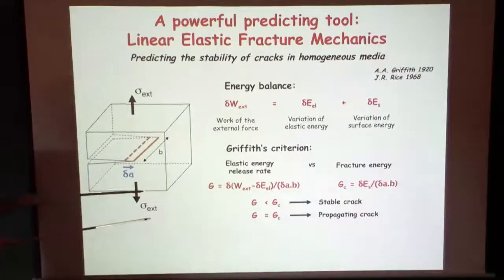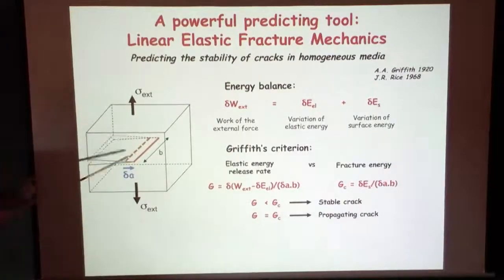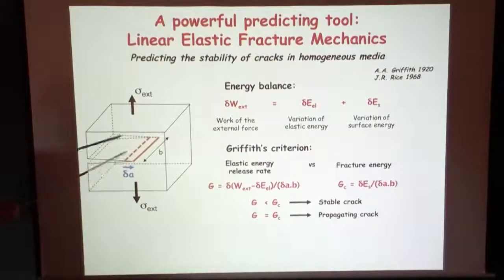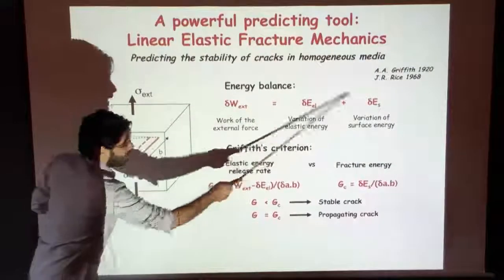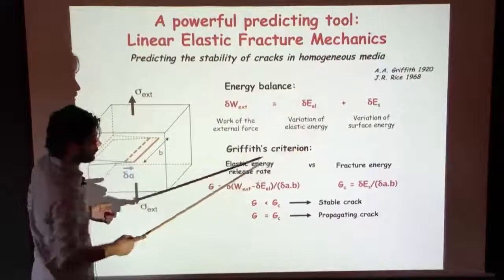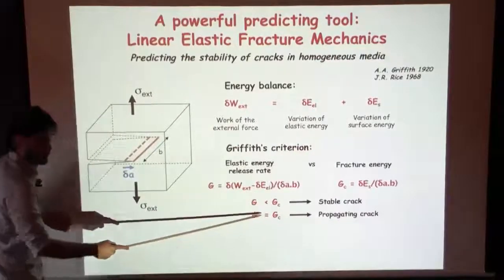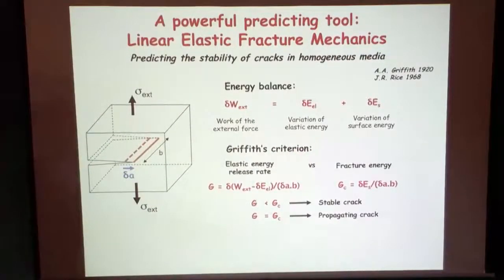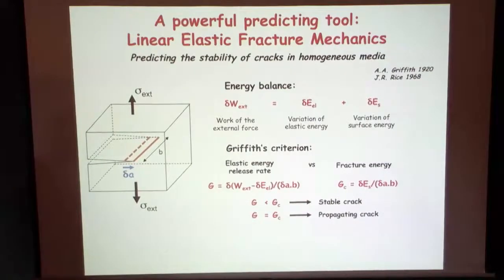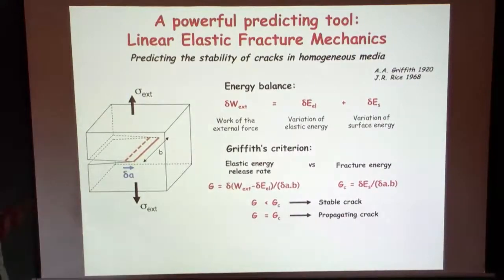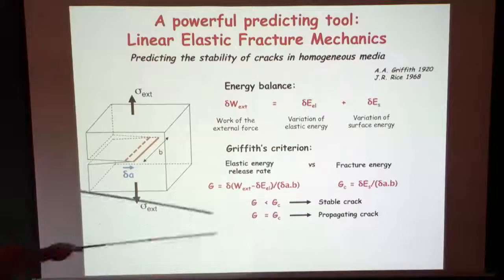If you have crack propagation, if you have crack advance, then your energy balance is satisfied, and so you have G equal to GC. This is what is written here. If you have propagation, you necessarily have G equal to GC. If G is smaller than GC, then the crack cannot propagate. Your thermodynamical driving force is lower than the rate of dissipation you need to plug into your system to make the crack propagate. You have a stable crack.